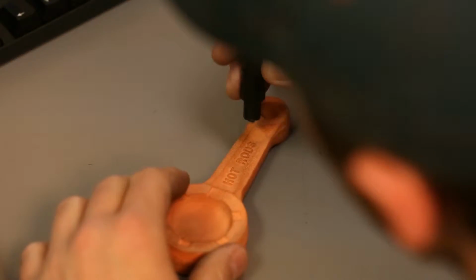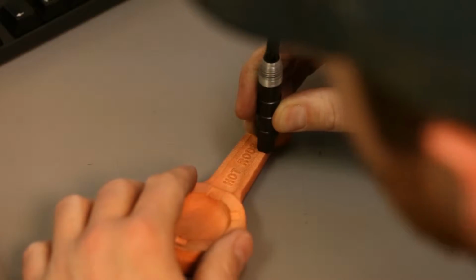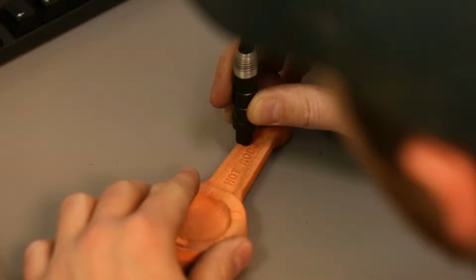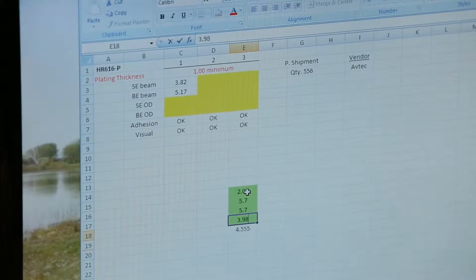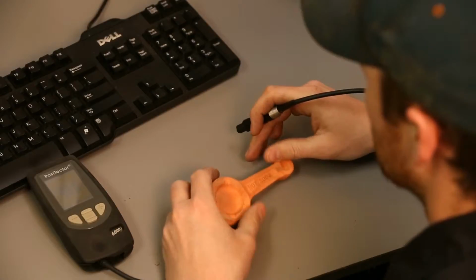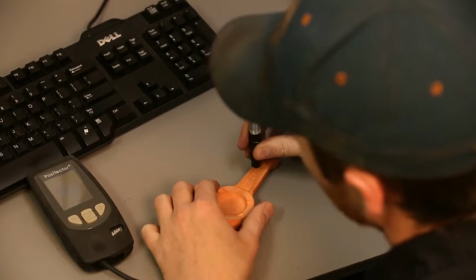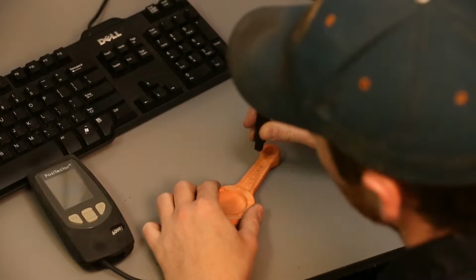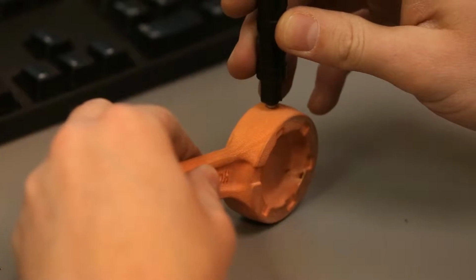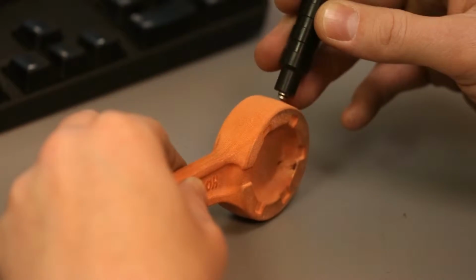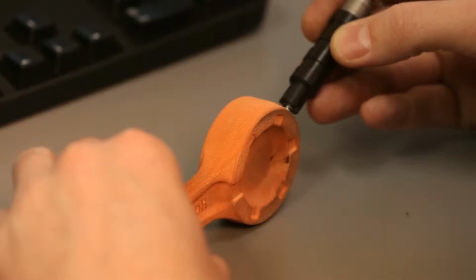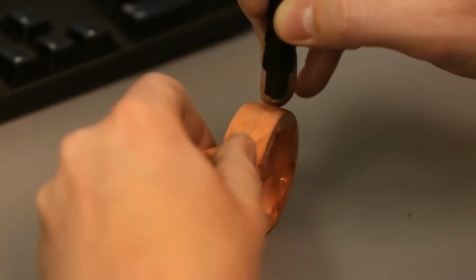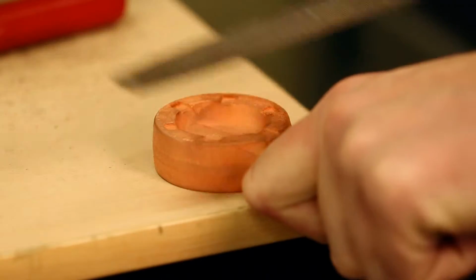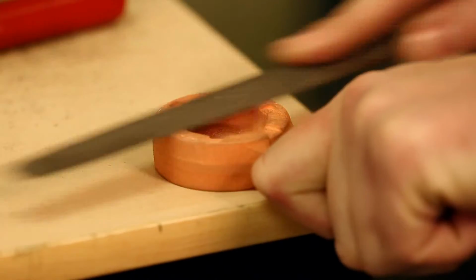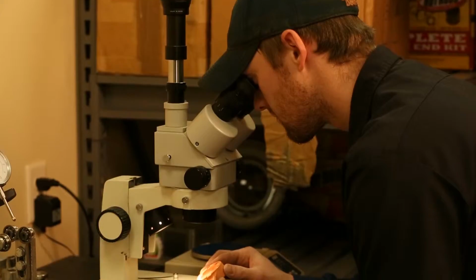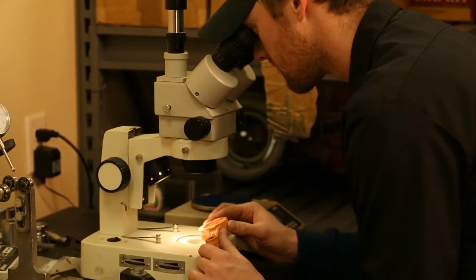The forgings are copper plated to protect the material from the carbon gases used during the heat treatment process. After the forgings have been copper plated, they are again inspected by Quality Control to ensure proper plating thickness and plating adherence quality. The thickness of the copper is critical to the hardness of the material and the overall dimension of the forging. The plating is inspected with a plating scanner to ensure a minimum thickness of 1/1000th of an inch. If the plating is too thin, the entire rod will become too hard and brittle and can lead to breakage. Adhesion quality of the plating is inspected using a file to ensure the plating won't flake off during the machining processes. Any rods failing inspection are sent back to have the plating stripped off and then replated.